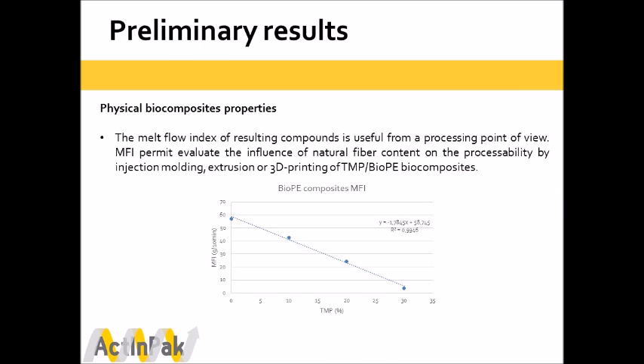The melt flow index of the resulting compounds is useful from a processing point of view. Melt flow index permits us to evaluate the influence of natural fiber content on the processability by injection molding, extrusion, or 3D printing of TMP Bio-PE biocomposites. The results show the evolution of melt flow index when TMP fiber content was increased. As can be observed, results show a notable decrease in melt flow index values as the TMP fiber content increases. This reduction of material fluidity implies some adjustments in pressure for injection molding, and temperature and time of processing for extrusion or 3D printing.